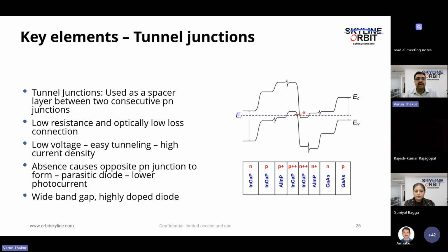Now coming to the next element, tunnel junction. So tunnel junctions are what I showed earlier. They are basically the spacer layers between two different PN junctions. So what happens is that if you have a PN junction and there is a PN junction below also, if the N of the top layer touches the P of the bottom layer, then they also cause loss of charge carriers. So to prevent that, we make something called a tunnel junction, which is a low resistance and optically low loss connection. So we don't want the charge carriers to be lost due to resistance in the circuit. So the resistance is low. So how do we make that? We make that by making it a very highly doped junction, right?